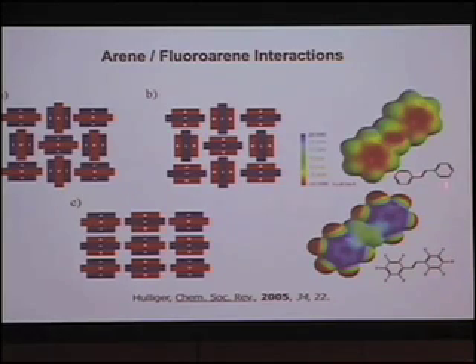So if you try to crystallize either diphenylstilbene or fluoro-substituted stilbene, those types of molecules tend to crystallize into a center-to-edge herringbone type of structure like that, because they try to avoid those negative charges sitting on top of each other. However, if you co-crystallize diphenylstilbene and fluorostilbene, then they form a perfect column-type stacking, which allows you to have very nice self-assembly. So if you consider one pair of the benzene and the fluorobenzene rings, that kind of interaction has an interaction force of about 3 to 6 kilocalories or more.